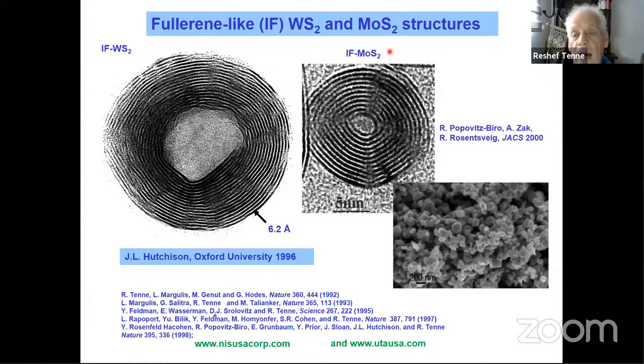And we call them IF molybdenum disulfide or IF tungsten disulfide because they are Fullerene-like structures. And indeed, it took us a long time to synthesize them in large amounts. At first we saw them in very small amounts, but slowly we developed the chemistry that allowed us to get this metastable phase. It's always a metastable phase, and I cannot go into the details, but theory will tell you that this is a metastable phase, but it's very, very stable at room temperature, and they form these hollow closed structures.